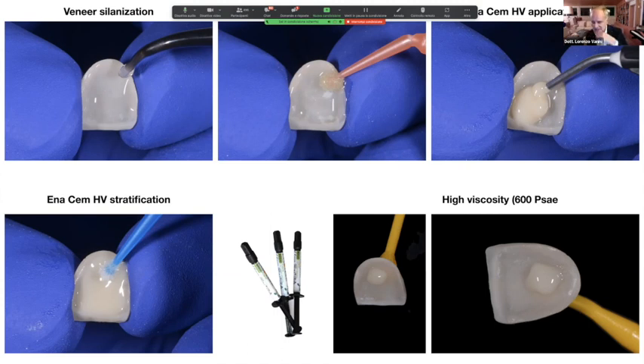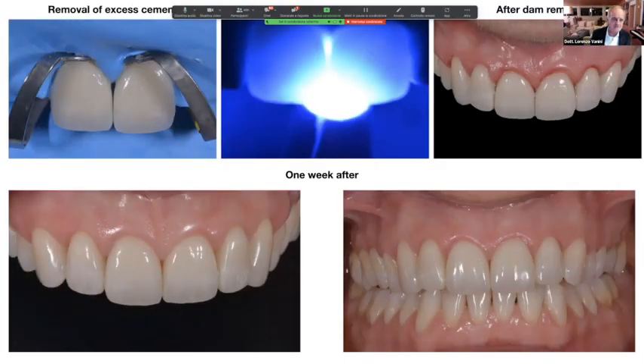You see that the viscosity is perfect. You have to stratify the cement inside in order to have a thin layer everywhere. And you see the laminates in situ. You have to remove the excess. And when you understand that the position is perfect, you can cure. After the removal, and 1 week after, you see the perfect integration in the gingival tissues and the perfect integration from the point of view of the aesthetics, shape, and color.